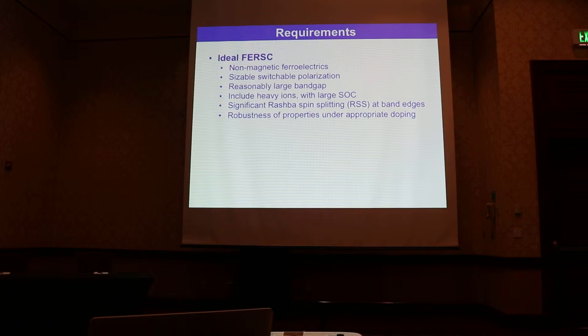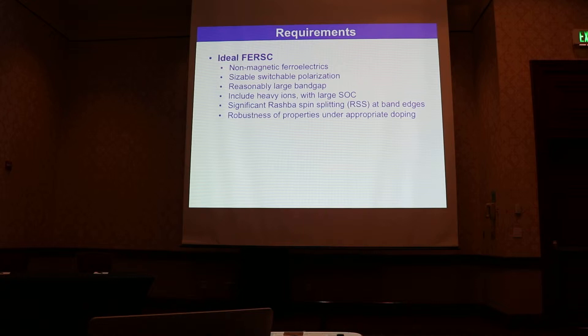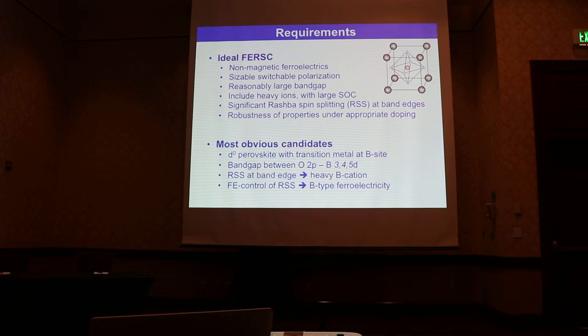We also combined structural analysis using group theory mode decomposition and tight-binding models to understand the results. For an ideal ferroelectric Rashba semiconductor, we look for a non-magnetic ferroelectric with sizeable switchable polarization, a reasonably large band gap, heavy ions with large spin-orbit coupling, and significant Rashba spin splitting at the band edges, so that when the system is slightly doped, these properties remain robust.